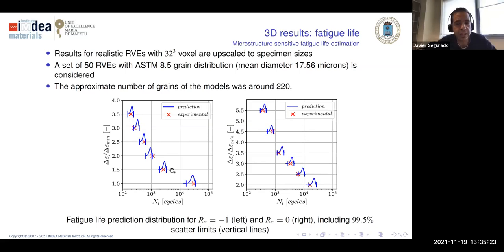So I'm going to explain these graphs because I have gone very fast. These are experiments. Here is the applied strain, and here is the number of cycles of survival. Of course, the smaller the applied strain, the longer the life, and this is the type of experimental trend. What we are doing here is fitting some of these values, maybe 1 or 2, for this law, and then we are predicting this probability distribution. So what we are giving as output is not only the fatigue life for this strain, but also the probability of having a fatigue life.